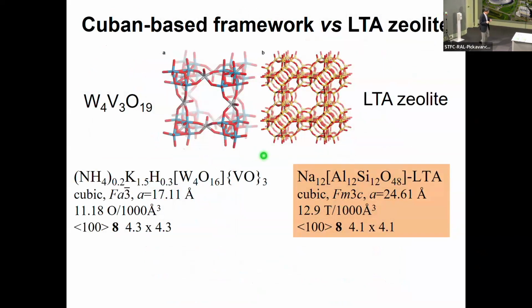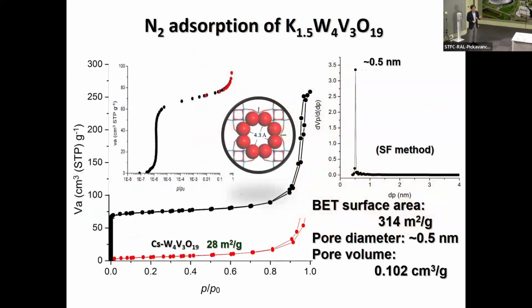This material has a topology very similar to zeolite A. Our material is cubic, and this one is also cubic. The pore size is a bit larger than the zeolite, so the void volume is slightly larger than that of LTA zeolite. Actually, this material shows high adsorption of nitrogen, with a surface area of more than 300. If you introduce heavy elements, large cations like cesium, inside the pore, then the surface area sharply goes down because the cesium just blocks the pore.